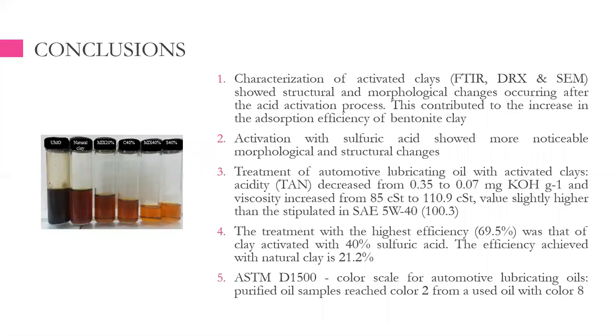The activation with the sulfuric acid showed the most noticeable effects on the morphology and structure of the natural clay, and this also resulted in the highest efficiency, something like 3.5 times larger for the clays that were activated using 40% sulfuric acid when compared with the efficiency that we obtained using only natural clay, which was approximately 20%.